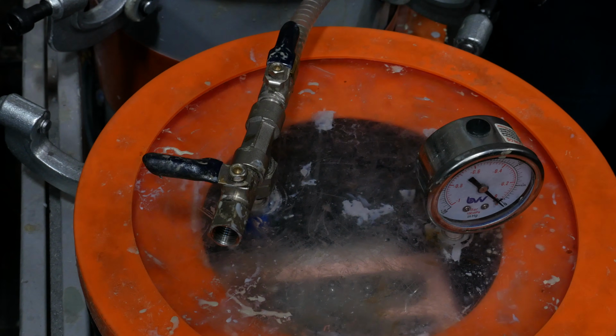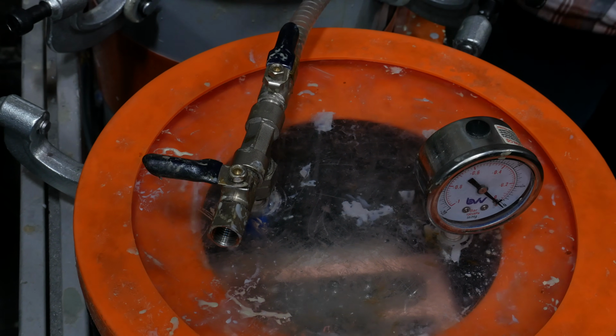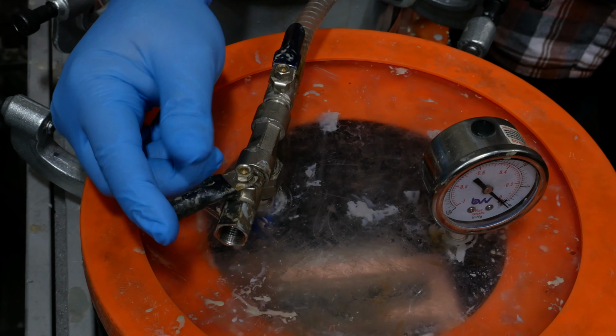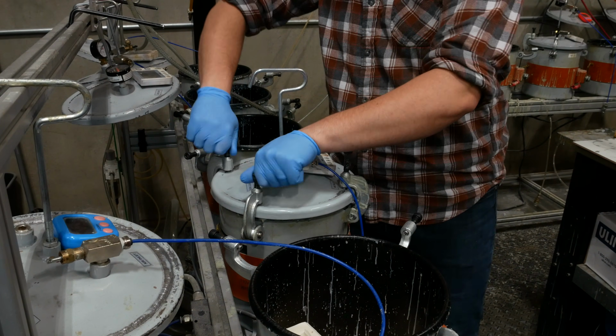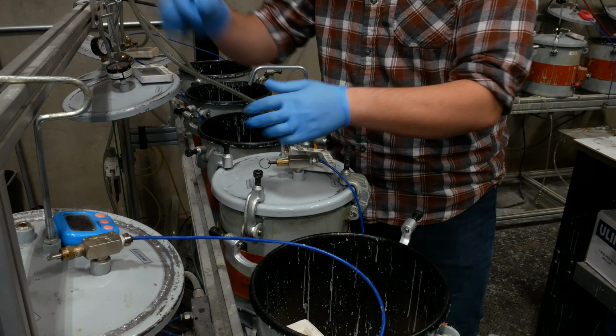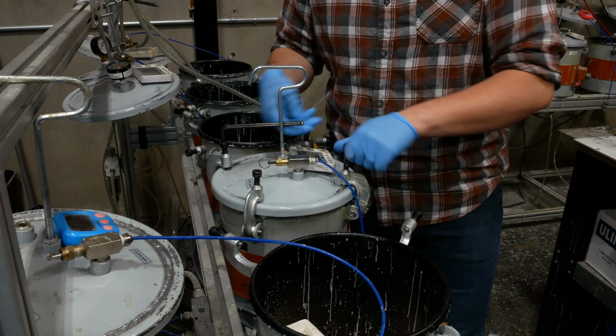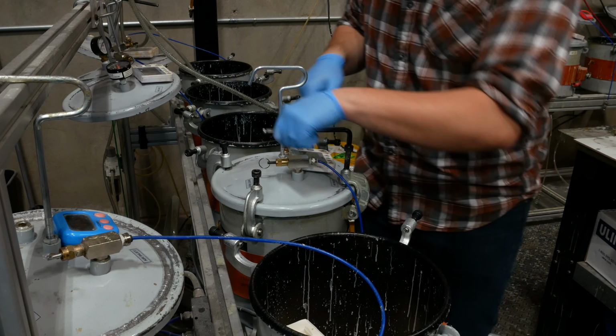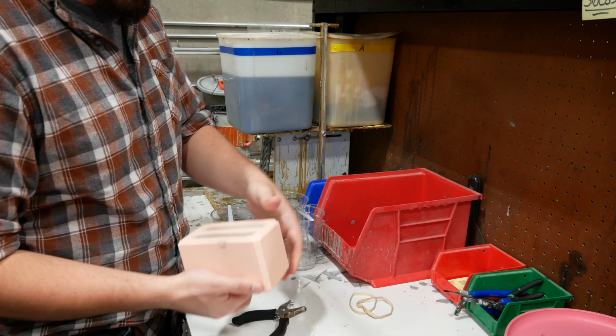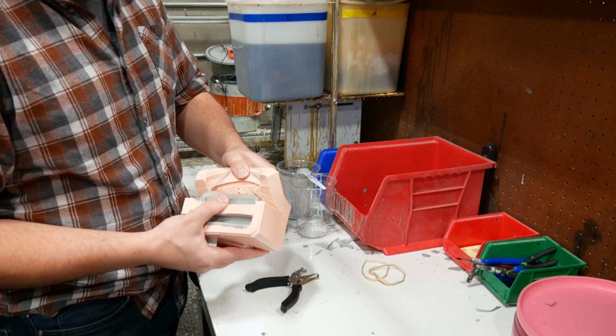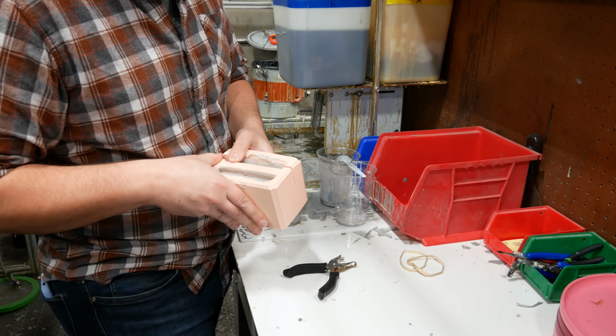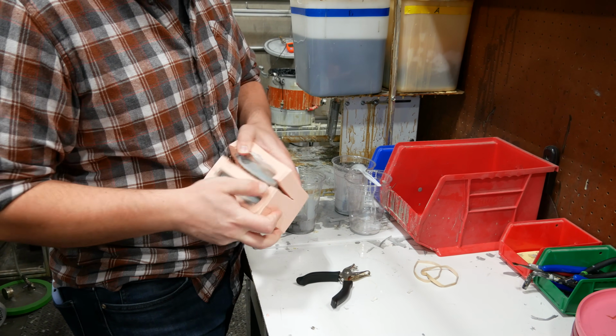A lid with a vacuum hose is attached, and the air bubbles are pumped out of the resin. Again, there can be a lot of air in there. After this, the lid is switched to pressurize the pot to prevent any new air pockets from forming while the resin is curing. It takes about an hour or two for the resin to fully cure, but after 30 minutes, the resin is solid enough to be removed from the mold, and the mold can be used again.